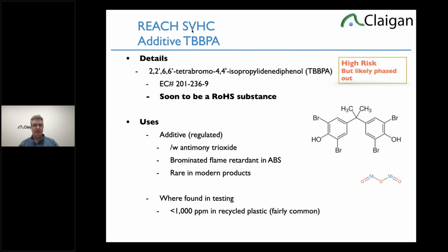Tetrabromo BPA, the additive version, was phased out years ago. It's really not used. We do see it in recycled plastic for sure, all the time, but in the sub 100 ppm range, so it's residual. Now, the main use of the tetrabromo bisphenol A is in BDDP, which is a tetrabromo bisphenol A dibromo ester, I believe. It's got 2 extra arms. So tetrabromo bisphenol A is a pretty poor flame retardant because it only has 4 bromines. The BDDP version of this, which has 2 extra brominated arms, has 8. It's what's used. It's a different chemical.